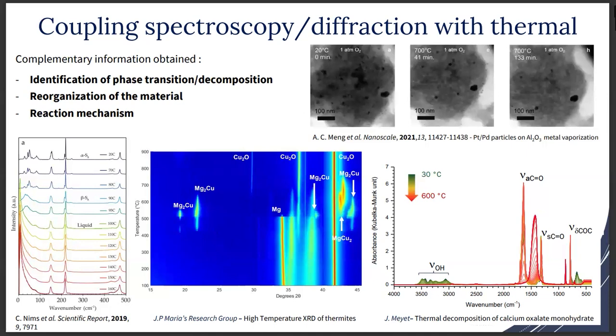On top is environmental TEM of platinum palladium particles on alumina, showing that under oxygen environment at elevated temperature, we have vaporization of the metal. All this information is possible in combination with thermal analysis, giving more insight into the material.